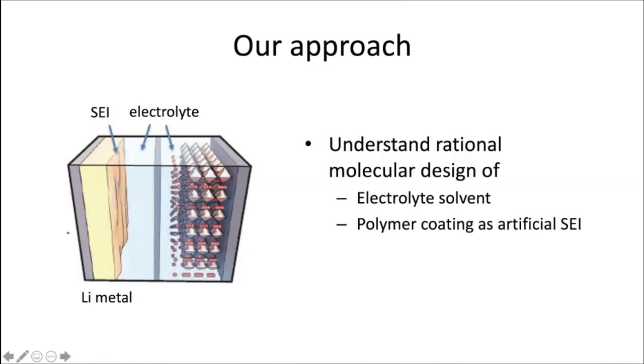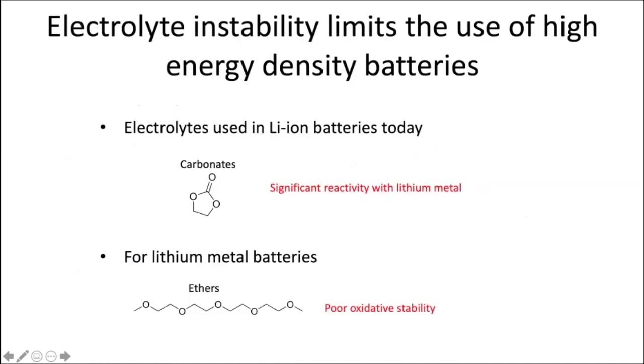As the artificial SEI. So traditionally, the electrolyte solvents that have been used for lithium ion batteries are these two classes. One is carbonate based, and this type of electrolyte can tolerate higher voltage, for example, NMC type of cathode. But the problem is it has significant reactivity with lithium metal.